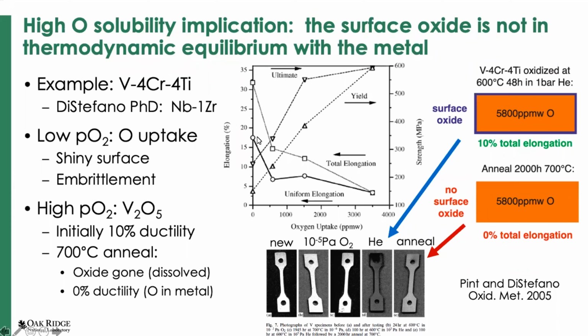So here's the elongation. You start off at about total elongation over 30%, and pretty soon you're down to less than 5%. And then at the same time, as you're picking up oxygen in the alloy, the yield and ultimate strength are increasing. And so it's not particularly surprising. When you do the same experiment in a high partial pressure of oxygen, or in this case, we did it just in 1 atmosphere of helium, you can grow an oxide on the surface. And so picture of it right here, there's an oxide on the surface, and you can calculate that that's the equivalent of picking up about 5,800 parts per million of oxygen. And that's way off the scale of this plot here, but we still had 10% total elongation, because most of the oxygen was actually on the surface.